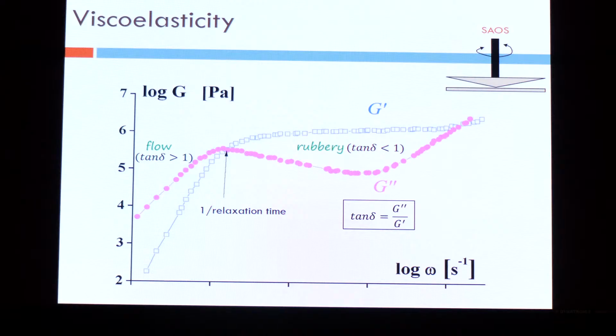And this graph gives very interesting insights into the flow properties of the material. At very low frequencies, that is on the left side, frequency is the inverse of time. So very low frequency is very long times. So I'm giving enough time for the polymer to relax. And therefore, in this case, the polymer behaves like a liquid. The liquid response is the G double prime, and you can see on the left side, the G double prime, the liquid response, is higher than the elastic response, which means the material behaves like a liquid. But at some frequency, they cross over. And beyond that frequency, it reverses.